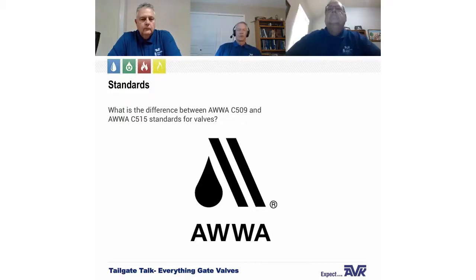And AWWA doesn't really use performance standards. They used prescriptive standards. So they said this is what your wall thickness will be. So manufacturers said, well, we're making these things out of ductile iron. It's a far stronger material. There's no reason for the walls to be that thick. Why don't we create another standard, C515, for reduced wall thicknesses for all ductile iron valves? So that's what C515 is. It's ductile iron only. And C509 is both gray iron and ductile iron, and it has thicker walls. It should be pointed out that if you have a ductile iron valve that complies with C509, it does comply with C515 because C515 is a minimum wall thickness. And that's about the size of that one.